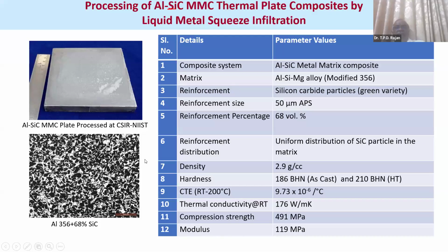Also, the same methodology we used to make, as I mentioned in the initial slides, the aluminum SiC thermal management component. Here we use an aluminum silicon magnesium alloy, a green variety of high thermal conducting alloy, with 50 micrometer particle size, and reinforcement concentration of almost 68. We are able to make a uniform distribution of the material with density around 2.9, hardness 186 BHN, in heat-treated condition 210, CTE 9.73 times 10 raised to the power of minus 6, thermal conductivity 176, compression strength 491 and modulus 119.